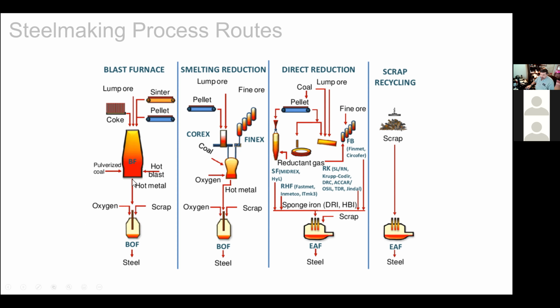And out of the blast furnace, you have hot metal or liquid pig iron. As I said, typically 4.3 to 4.5% carbon. And that material gets charged into a BOF. BOF stands for basic oxygen furnace. It's sometimes also called BOS, basic oxygen steelmaking, or a number of other names, which I'll cover in a few minutes here. And what we do is, because we're going to blow this hot metal with oxygen, we're going to remove a lot of carbon. We're going to generate a lot of heat. We're also going to remove silicon, and the oxidation of silicon generates a lot of heat.